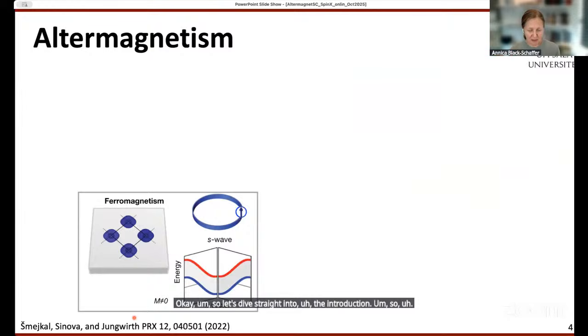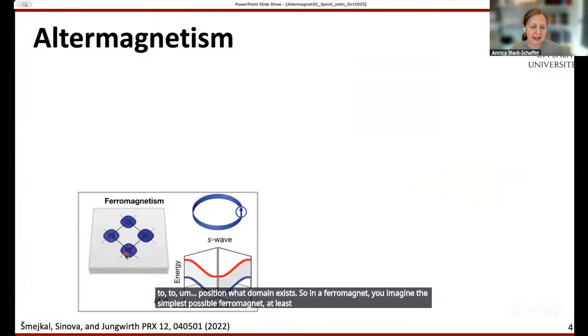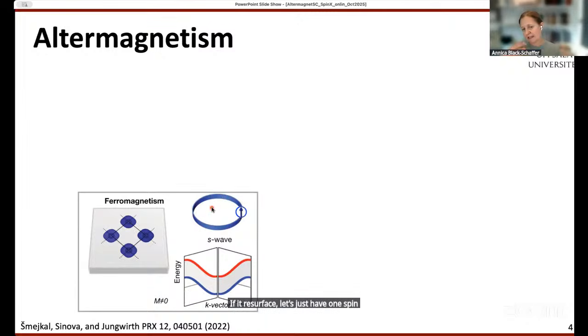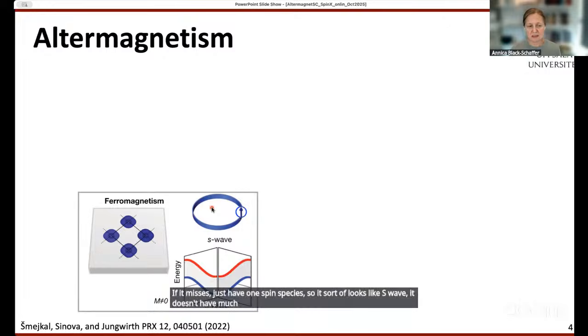These pictures you've probably seen before, but just trying to position what the altermagnet is. So in a ferromagnet, you imagine the simplest possible ferromagnet, at least, that you have the same magnetic moment on every site in space, as in the picture here. This will give you some spin-split Fermi bands, and if you put the Fermi surface around here, you can even get a Fermi surface with just one spin species, so it looks sort of like S-wave. It doesn't have much structure in spin space.